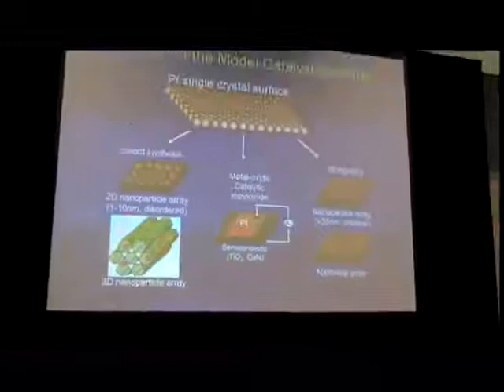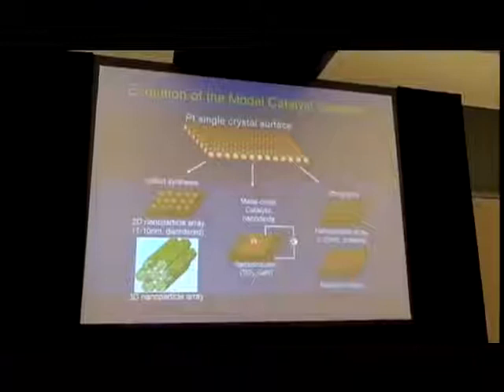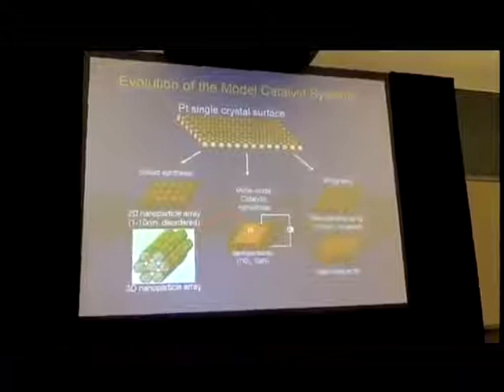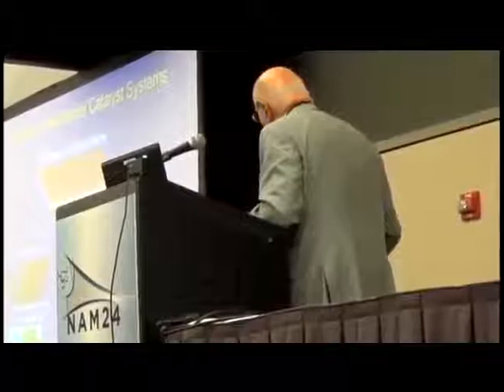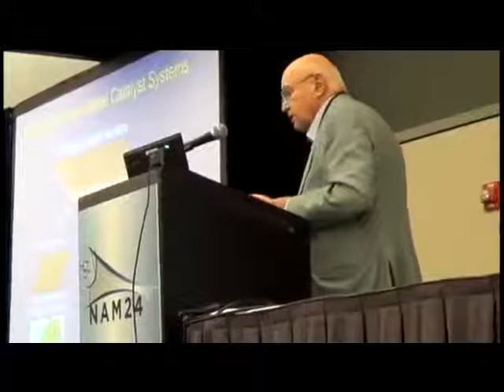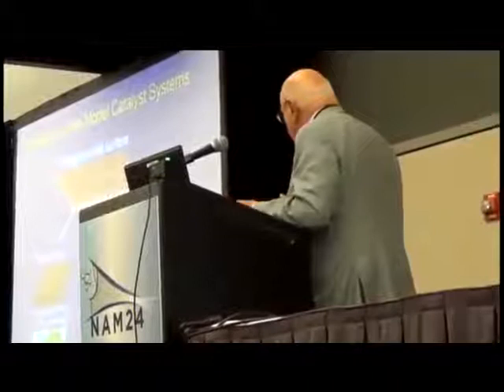We use model systems, starting with single crystals. One major finding was that ordered single crystals do virtually no catalytic chemistry, which made us go to defects. Then we went to nanoparticles — whether made by electron beam lithography or photolithography, this is a very nice science and technology. Then you go to three dimensions, which increases the surface area, very important for covalent catalysis but not for acid-base catalysis. Acid-base catalysis depends on charges and is virtually independent of surface area.